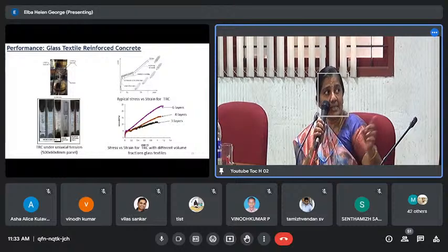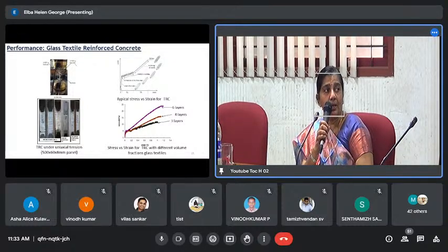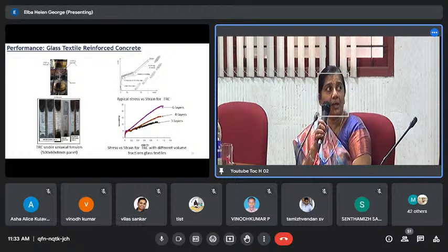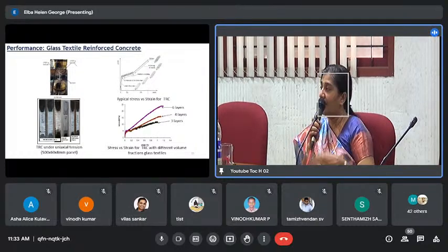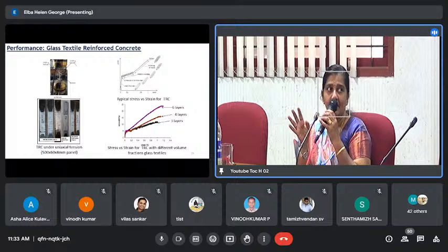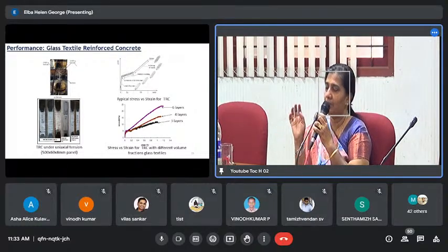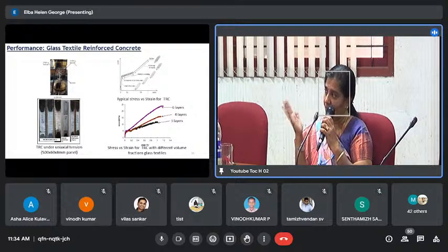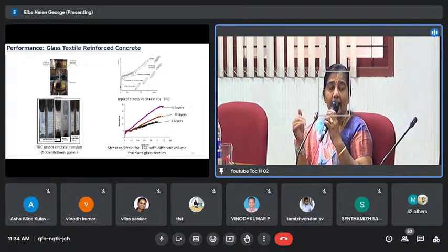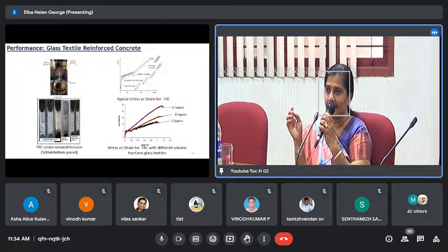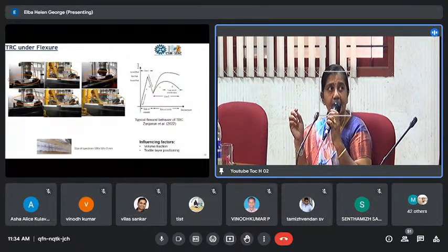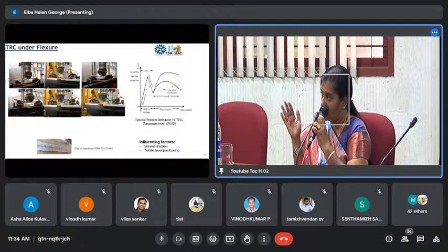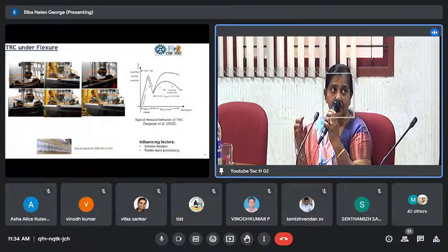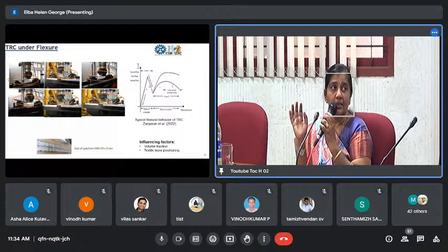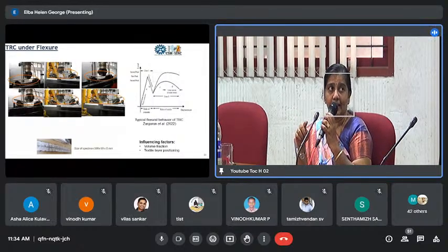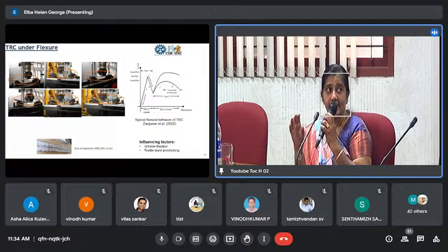tensile strength. You can see with 3 layers of textile, you are able to achieve tensile strength of around 12 MPa. With 6 layers, you can achieve around 22 MPa. I'm sure all of you are aware that concrete has tensile strength in the range of around 2 to 3 MPa. So with TRC, you can achieve up to 20-25 MPa using glass textile and around 30-35 MPa using carbon textile. Now under flexure, this is how it behaves. If you subject this TRC to flexure, this particular panel keeps on bending without breaking. There are many multiple cracks you can get when these kinds of panels are subjected to flexure.